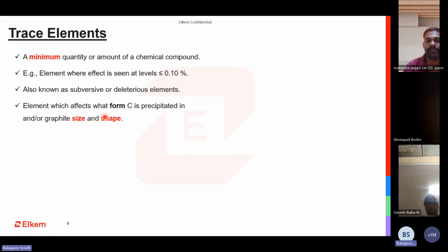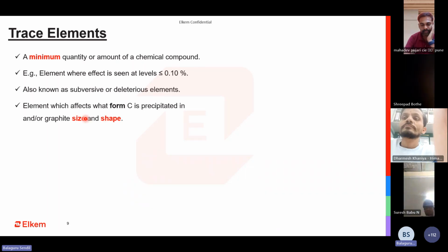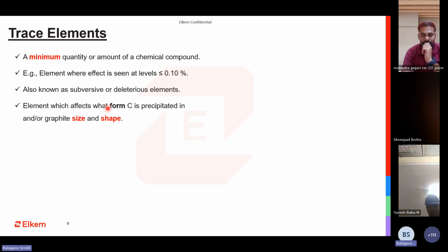So in spite of us having a graphite microstructure, when it is cooling down, it can make the graphites become too big, that is, nodules become extremely enlarged, more than 70 microns, or the flakes become very thick. That is with respect to the size, and the element can also influence the shape. How round is the nodule? It could form a perfect nodule and then break it. It could form a perfect nodule and then have a spike on it, which is going to get dangerous. So this is what an element typically does.